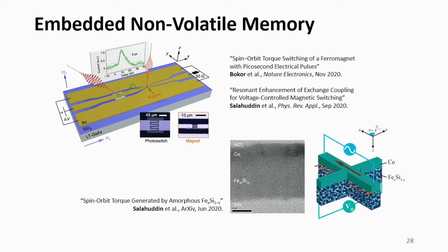So this just shows that nanomagnetic devices can actually switch pretty quickly and be scaled to very small dimensions. The image on the lower part of this slide is from Professor Salahuddin's group, who made the groundbreaking discovery that spin-orbit torque can be observed at room temperature using fairly common materials. So he uses iron silicide and cobalt. There's a bilayer shown here. So this basically opens the pathway for implementing new memory technologies using fairly common materials that are already used in CMOS processes today.